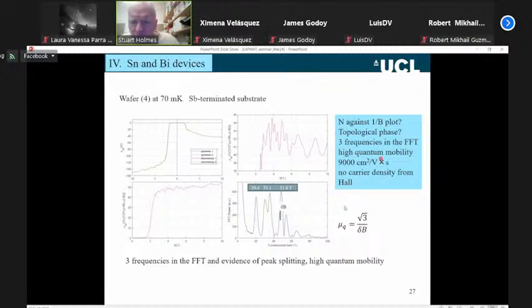What we can also do in this Fourier transform is calculate the mobility. From the width of the Fourier transform, we can get the quantum mobility. And the quantum mobility here is about 9,000. So this particular wafer has a much higher mobility, and we've seen this extra structure coming in. The first wafer had about 4,000 mobility.